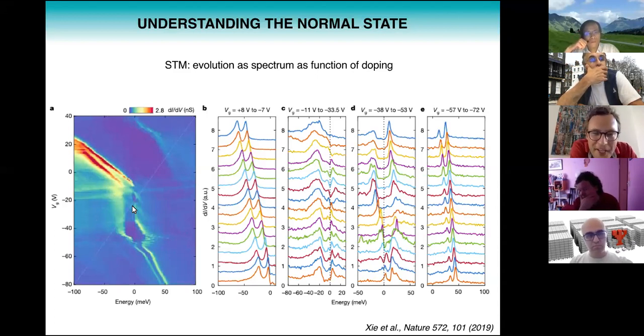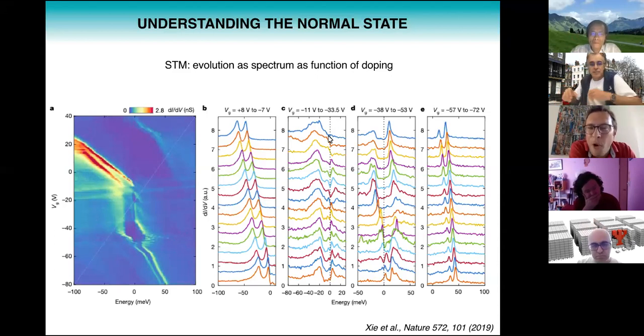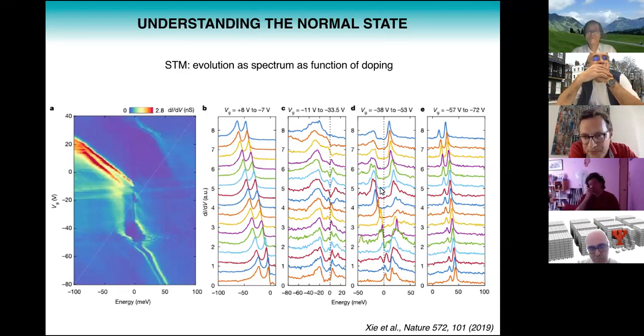What is very interesting though is that when this Fermi level pinning happens, if you look at the spectrum, the Van Hove singularity seems to completely disappear in this measurement. So that's very strange. And then the Fermi level stays pinned for a while until you move close to the charge neutrality point, which is this region here. And then the spectrum becomes very symmetric and is unpinned.